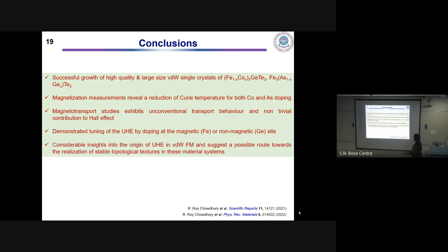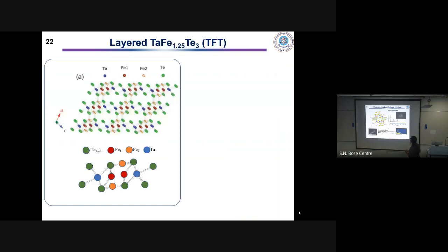So now I would like to come to the second part of my talk, but before moving on to that, I would like to answer your question about what might be the reason for the stabilization of these kinds of topological structures in Fe3GeTe2. Very recently, theoretical calculations have shown that one of the possible reasons is a competition between the dipole-dipole interaction, the exchange interaction, and the magnetic anisotropy altogether, which plays a key role in stabilization of skyrmion-like textures in the system. This is a very recent one, which is going on right now. And another possible reason I would like to show you, but I have to go.